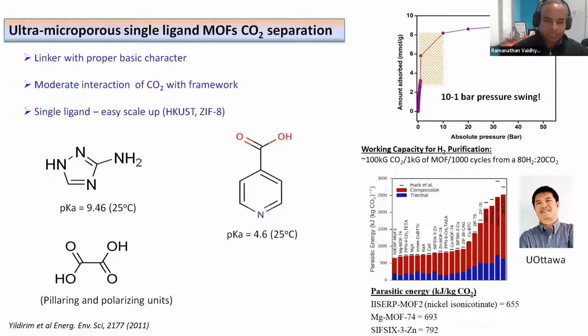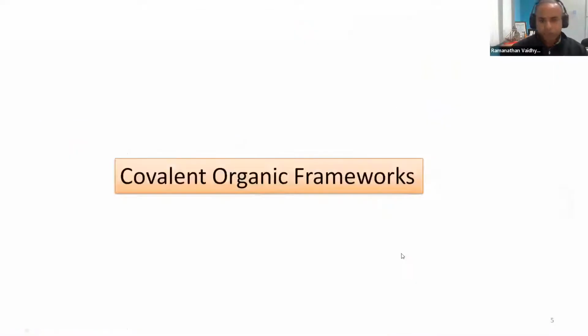Professor Seda Keskin gave a very nice talk and concluded by asking what parameters we should follow to judge the performance of a porous MOF for specific gas separations. One thing we follow is the working capacity. For example, for hydrogen purification or pre-combustion capture, a 10-to-1 bar pressure swing would be our attractive target. The other parameter we look at, which is a holistic parameter, is the parasitic energy, which we calculate with a lot of help from Professor Tom Wu from the University of Ottawa. Today's talk, however, will be on covalent organic frameworks.